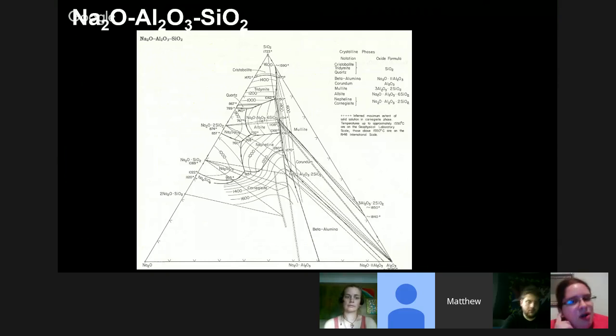And actually, if you go into the readings from class 1, those kids books that I have in there, if you read the one on sodium, it talks about sodium silicate. But here's what's interesting. Why we don't do that, and this will come up in the next lecture, the one after, is because of the question of glaze durability. A sodium silicate crystal is terrible from a durability standpoint. It dissolves in water. So even if we precipitated this crystal that was based in sodium, it would actually fall apart from daily use, and shockingly enough, that is literally